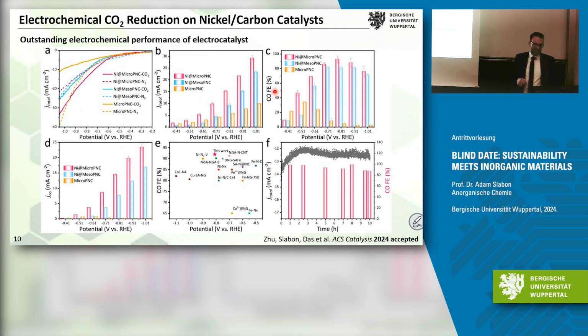Faraday efficiency, which is like the selectivity of CO2 reduction to carbon monoxide, and it's actually quite high. But the selectivity has to be coupled also to the performance of the current, which you can see here, it's like above 20 milliamps per centimeter squared, and this positions this catalyst right now among the best performing ones.